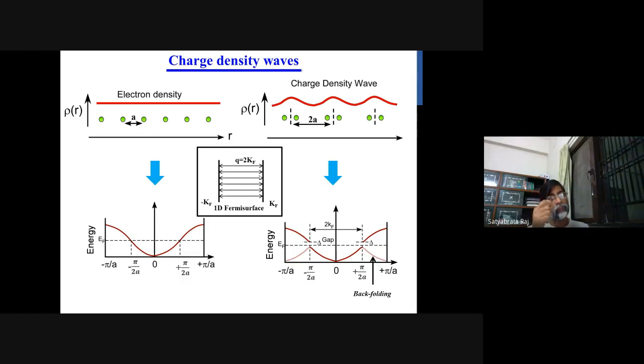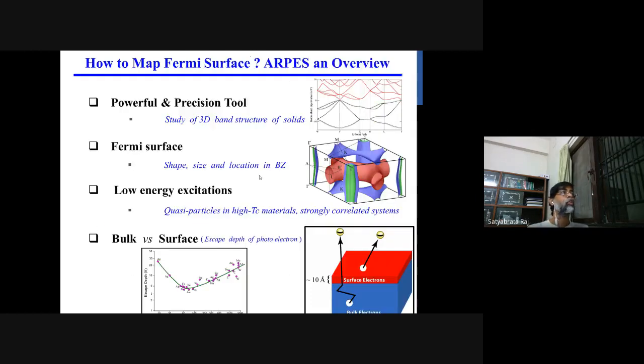CDW scattering Q vector from the scattering experiment. So ARPES is very helpful to understand not only the band structure and the Fermi surface, but even the three-dimensional Fermi surface, and you can map the surface Fermi surface and the bulk Fermi surface by tuning the photon energy.